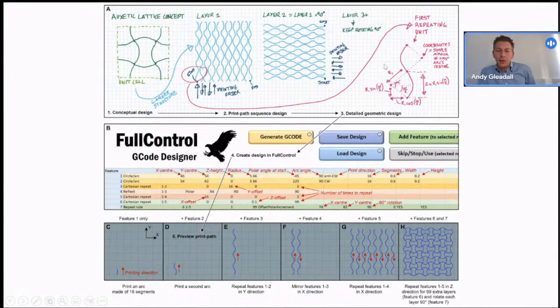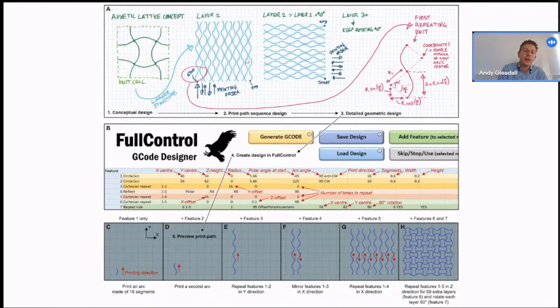And this shows the workflow of designing that toolpath. So starting at the top left, we knew this was our unit cell that we wanted, but it was obvious printing one unit cell and then the next one and then the next one wasn't a logical print path. It was better to do one layer going all the way up and all the way down, all the way up and all the way down, and then the next layer doing all the horizontal ones. Because that would be the nice, neat way to print this structure without the nozzle always changing direction and jumping around and having to stop and start extrusion and everything.